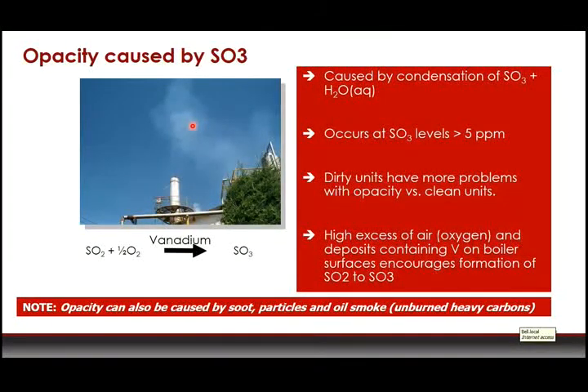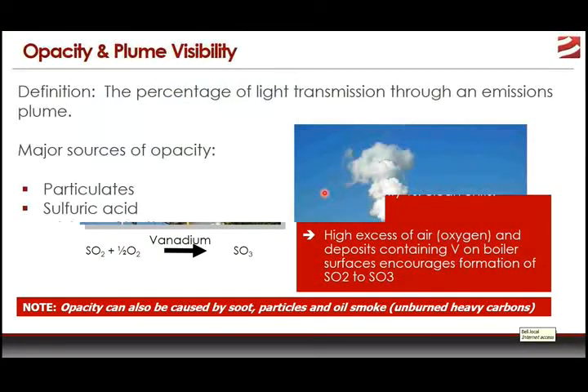Opacity typically becomes a danger when SO3 levels in the exhaust gases are above a few parts per million. And typically, a dirty unit is more likely to have SO3 levels greater than 5 ppm. It's more likely to have any of these kinds of problems. So dirty units tend to have a greater chance of having opacity problems than clean units do, which is probably why people object to them, because they intuitively recognize that if they see stuff coming out of that stack, there's something going on in there that's probably not good.